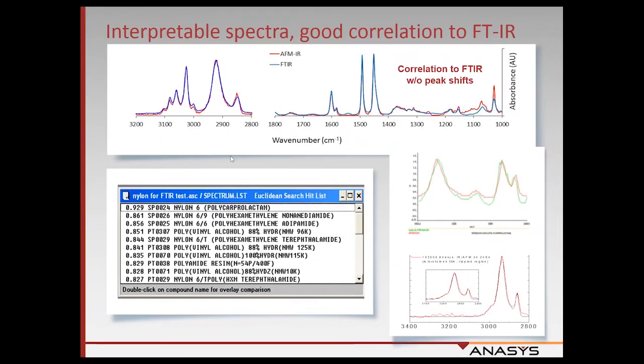And then a really nice thing about this AFM-IR technique is that it correlates very well to conventional FTIR, as I said, because it's measuring the same fundamental property, the absorption of IR light. And so because of that, you can use the same sort of analysis techniques to look at AFM-IR spectra, to look at the relative peak heights, to look at the peak positions, et cetera, to look at the pattern of peaks as a fingerprint, to identify unknown materials, for example.